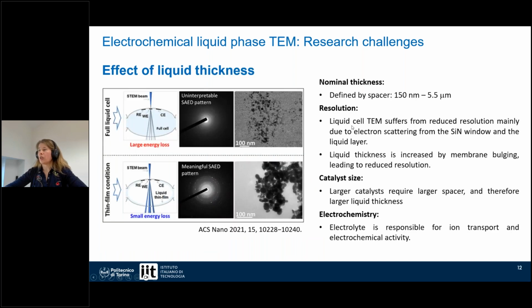With this, I come to think about what would be the influence of the liquid thickness within this cell, and two aspects need to be taken into consideration. The first is the electrochemistry that we want to run, where the electrolyte is responsible for the ion transport and electrochemical activity, so we actually want to have electrolyte. From the other side, we want to think about the resolution. And we know that liquid cell TEM suffers from reduced resolution because of the electron scattering from the silicon nitride window and also from the liquid layer.